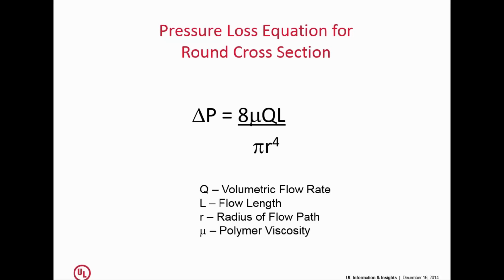Now, if you're going to make a full part, obviously you have to have pressure everywhere in the cavity. And the general rule that we observe when we put cavity pressure transducers in a mold is that in order to have what we call a packed out part, a part that looks good, is dimensionally stable, and reflects the surface finish of the tool, you typically will want to have about 2,000 to 3,000 pounds of plastic pressure at that point in the cavity. So if you have a machine that can generate 27 or 28,000 psi, you can afford to lose a lot more pressure and still get there than if you have a machine that can only generate 16 or 17,000 psi.